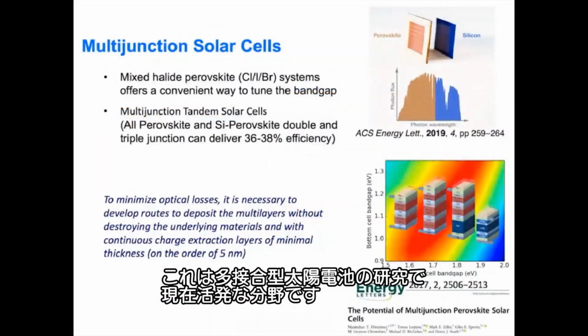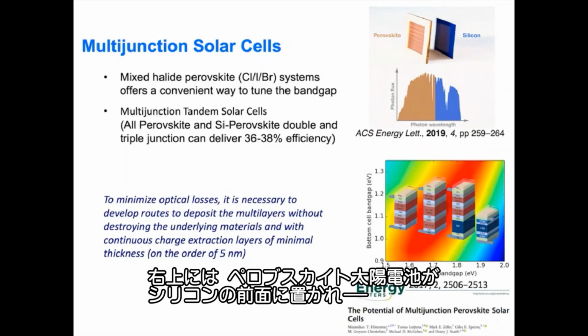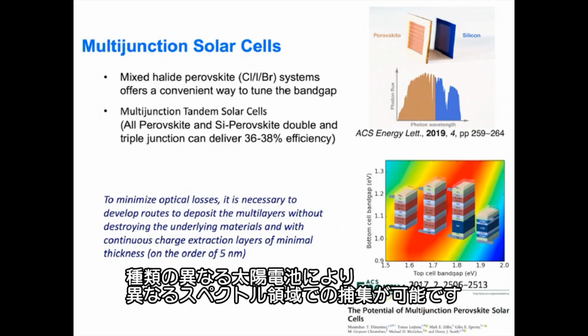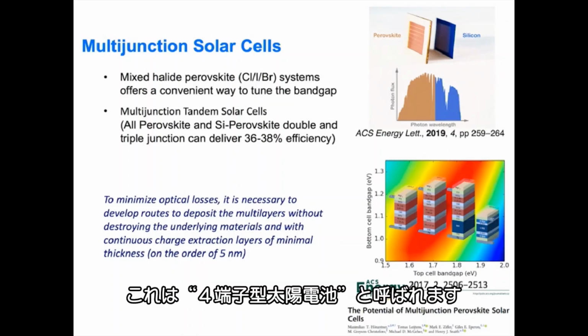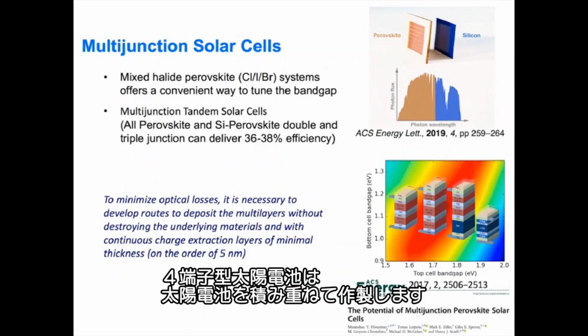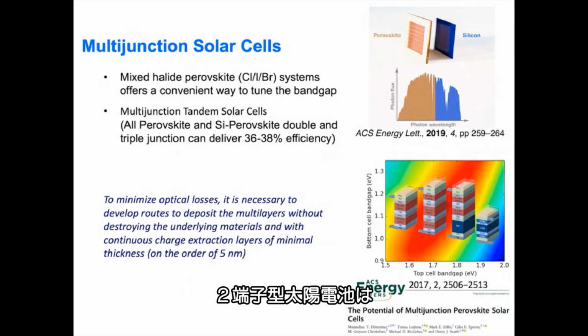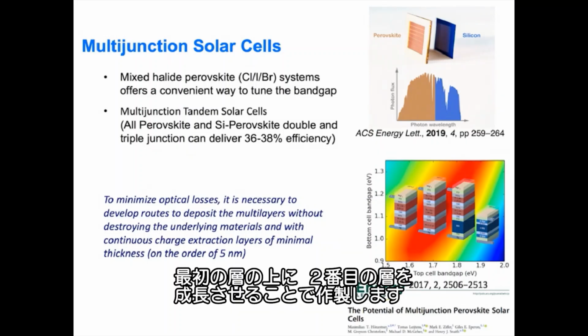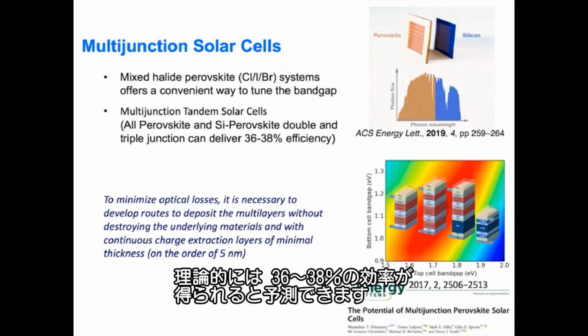So this is another active area, which is multi-junction solar cells. Again, in the top corner you see here the perovskite solar cell is put in front of silicon so that different regions of the spectrum can be harvested by different solar cells, and they call it a 4-terminal solar cell. In the 4-terminal solar cell, basically you are putting one solar cell on top of the other, whereas in the 2-terminal cell you really grow the second layer on top of the first, and there are only 2 contacts to make it.